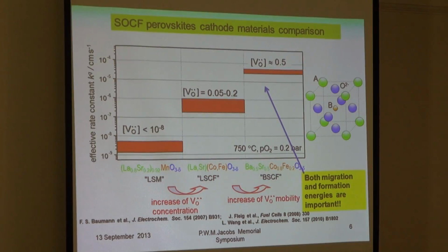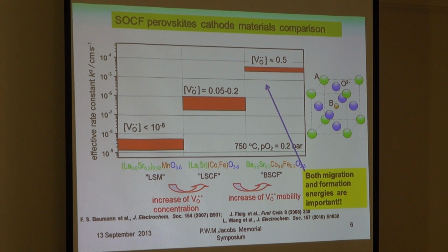This is our dream. And this is a very clear message and very clear summary from experimental studies of the efficiency of oxygen reduction on the surface of cathodes for three classes essentially of perovskites used for these applications. The first one is so-called lanthanum manganate doped with strontium, whose abbreviation is LSM, usually just very simple.